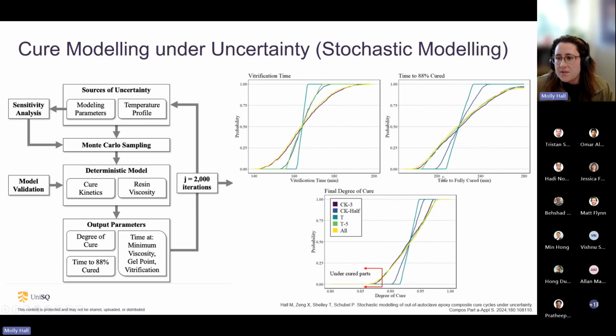So just to draw attention to a few things. For example, time to 88% cured. The significance of this is that 88% cured for this polymer is commonly considered what we call fully cured. It's very uncommon to get to 100% converted in these polymers. We don't usually require it to. We tend to define a threshold where at this level we have the extent of properties that we're expecting from it.